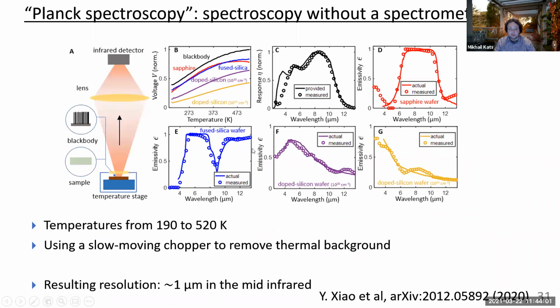So for example, fused silica has a vibrational mode at about 9 microns and another one at about 8 microns, and that results in this spike in the emissivity spectrum. And that's what this technique measures, all of that stuff. The only time this would result in some sort of weirdness is if each one of those modes had a different temperature, or an occupation at a different effective temperature, and then that would mess this technique up. But under normal circumstances, that's totally fine.